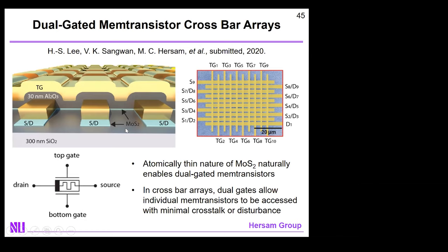lithographically, like we do with doping in conventional semiconductors. That, I think, is the key to scaling. And in fact, there's a paper from Wei Lu's group at University of Michigan in Nature Materials, I believe, where he indeed did this with lithium ions and multilayer MoS2, which is one possible way of achieving that functionality. So is that material MoS2 CVD grown, single layer or few layer? In these devices, it's single layer. In the Wei Lu device, where they are using ion intercalation, then it's multilayer. It's a few layers, yeah.